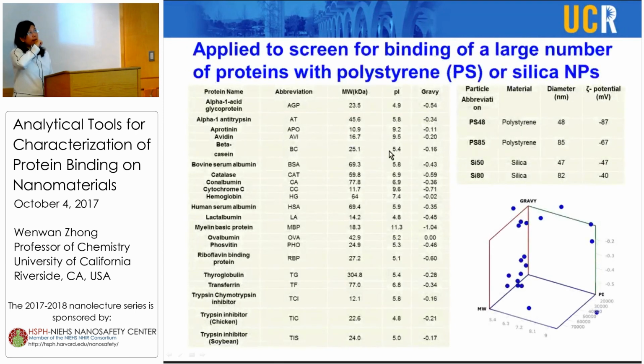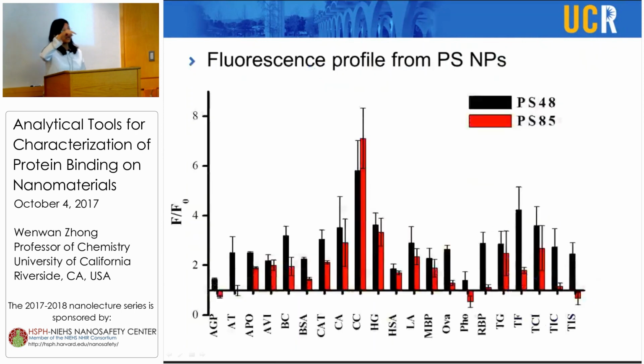And then we expand this screening to a larger number of proteins, and again here we want to have a wider coverage of molecular weight, PI, and hydrophobicity. Here in total we screened 21 proteins, and some of the signals are shown here. Again, for polystyrene particles, we could see enhancement in the fluorescence label, and in particular for the smaller one, we could see more fluorescence enhancement compared to the larger one.